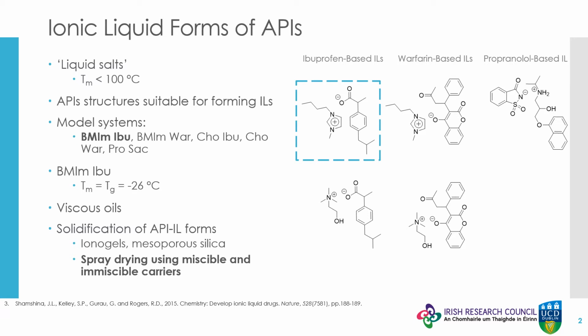To address this, we've developed a platform that uses spray drying to solidify API-ILs by forming a solid solution of API-IL in a miscible carrier or spray encapsulate it in an immiscible polymer. This approach was developed initially using the model compound 1-butyl-3-methyl imidazolium ibuprofenate, which is representative of API-ILs as it has a melting point of -26 degrees Celsius and is a viscous oil under ambient conditions.